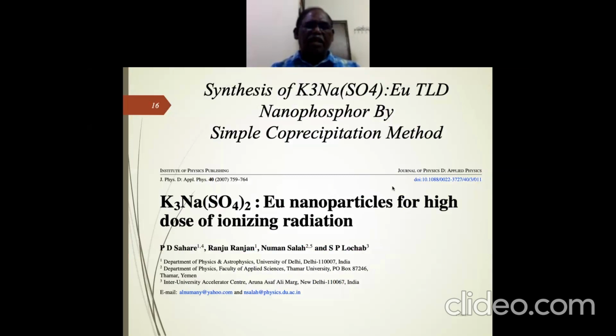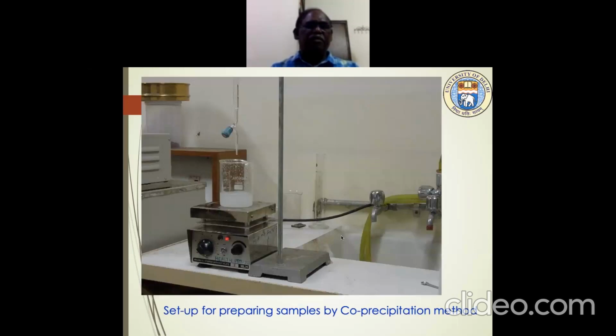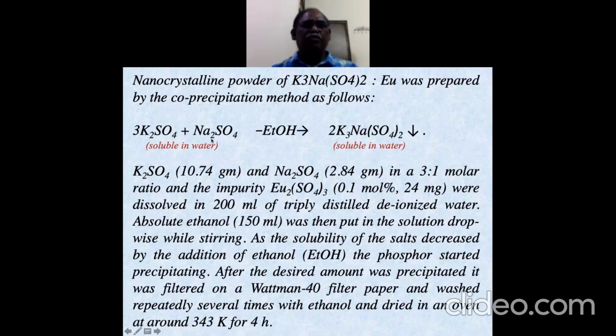Then with this same technique, I have chosen K3Na(SO4)2. This is another material I deliberately chose, because the technique is the same, but here your ingredients K2SO4 and Na2SO4 are soluble in water, and at the same time K3Na(SO4)2 is also soluble in water. So we didn't know what to do when both the starting material and the product are soluble in that solvent. But then we found the solution: if you add ethanol and go on increasing the quantity, the solubility of this material decreases, and at some concentration it starts precipitating, and you can really get some good nanoparticles. So these are the nanoparticles.